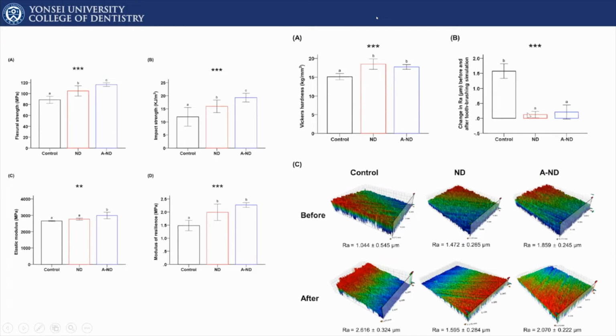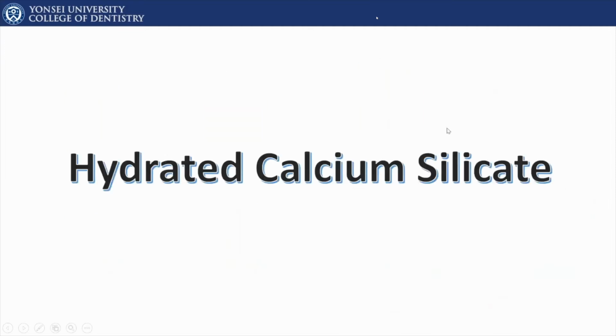It also had an impact on the Vickers hardness, and the changes in surface roughness before and after the toothbrushing simulation were pretty much minimal, which indicated that this is a very durable way of providing higher mechanical strength. So the provision of this improved mechanical strength with nanodiamond was very interesting, but we wanted to go further than that. We wanted to have some bioactive results, in terms of antibacterial and antifungal effects, in addition to this nanodiamond.